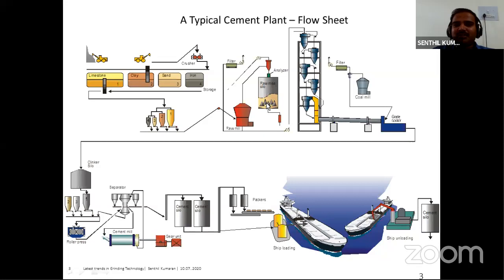Through the blending, we ensure the free flowing of the material, and we extract from these 5 cones. We extract from each side at once, so there will be ratios. We take from different ends all the time, so that the material homogeneity can be ensured, and the temperature inside and the pressure are also maintained. Here we maintain sufficient draft so that the material will not form a cake inside the silo. So it is continuously aerated. These are specially aerated designs.